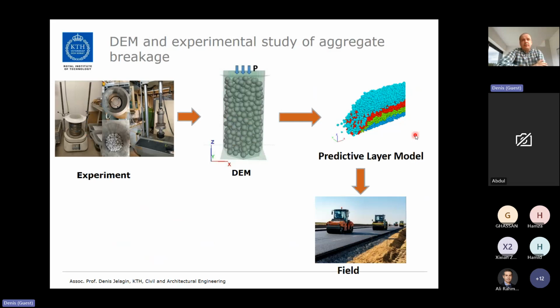We developed a combination of experimental and numerical procedures where we measure aggregate crushing in the lab in the uniaxial compaction test shown here. We have a steel cylinder where we load a certain size distribution of aggregates. We do a sieve test before the test, and then we apply a controlled compressive load to the material, loading it with roughly 20, 30 kilonewtons, etc. And then we perform sieve analysis after the test, and we see how much material has broken off.